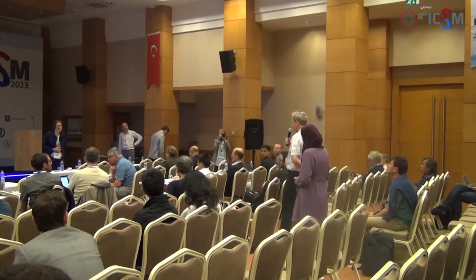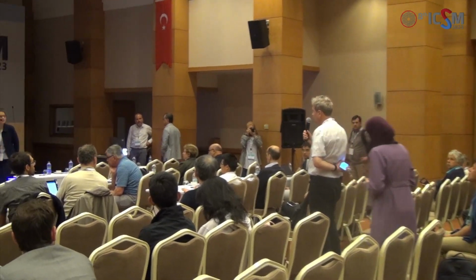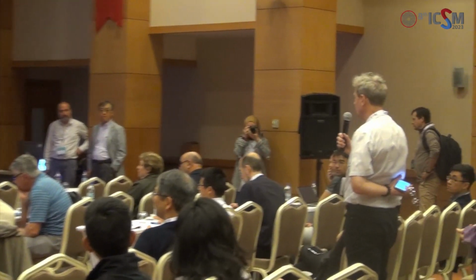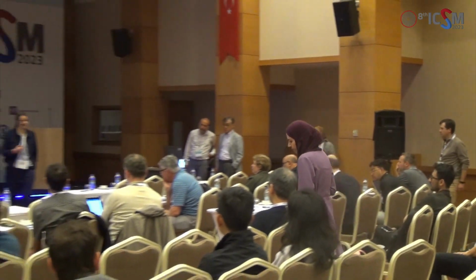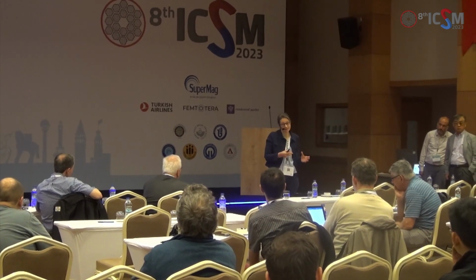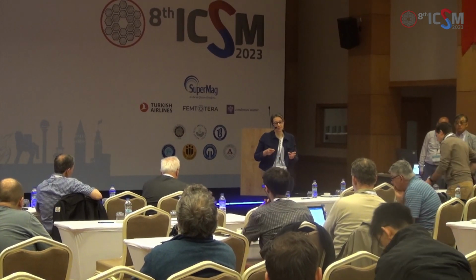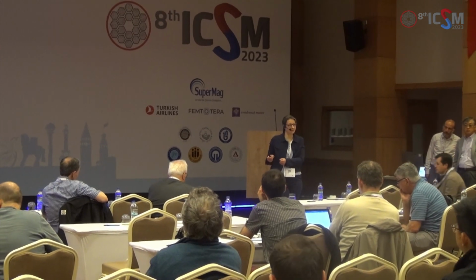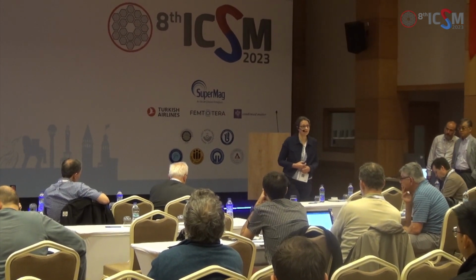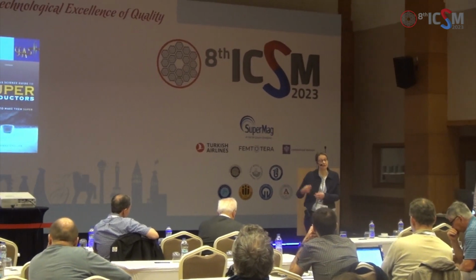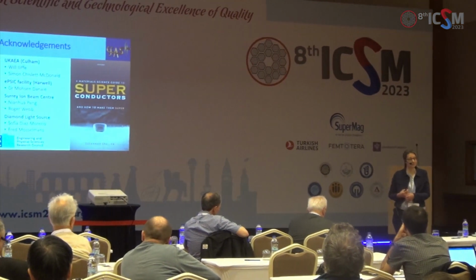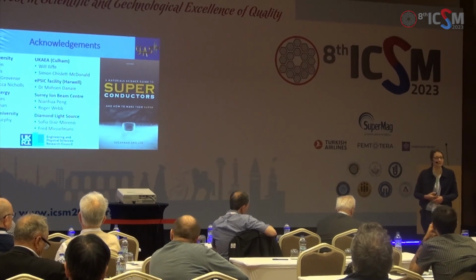Thank you for your talk. Could you please comment on the time required for annealing of your samples, compared to the damaging time? Okay, so with our experiment, what we normally do is we irradiate at the beamline. That can take a few hours to get to the flux we need with ions. We then take our sample back to the lab, and the next day we cool it down again. So it's a one-day annealing at room temperature. We've done it for longer, and of course you get slight improvements for longer times, but most of the recovery happens in the first day.